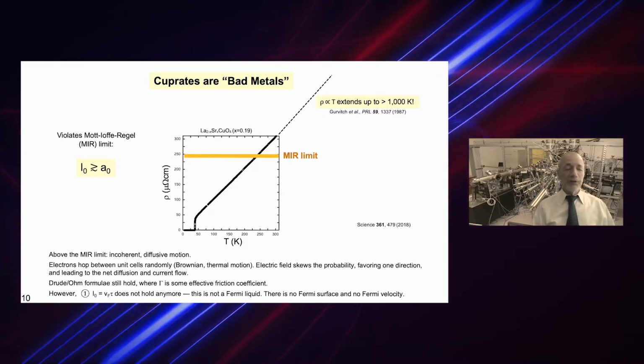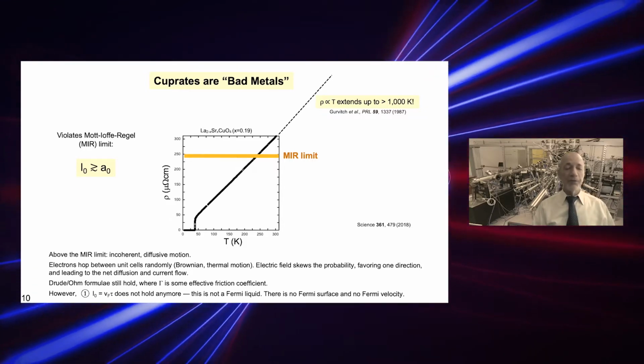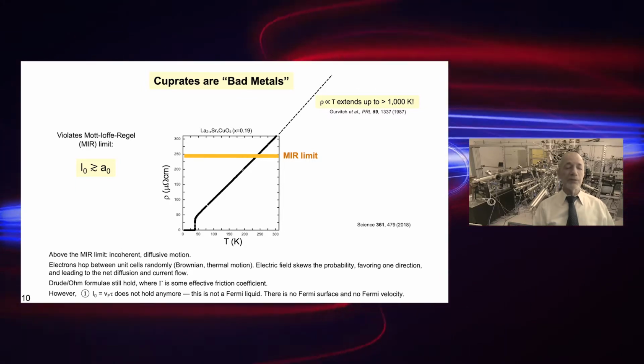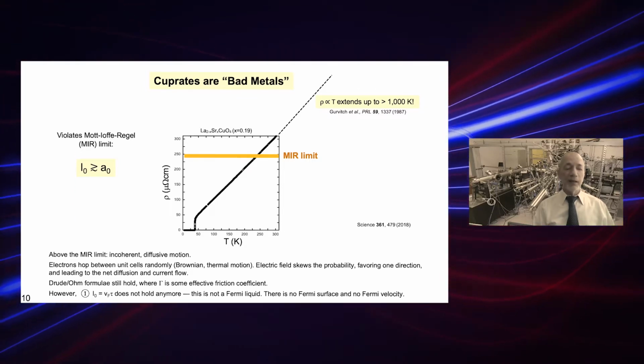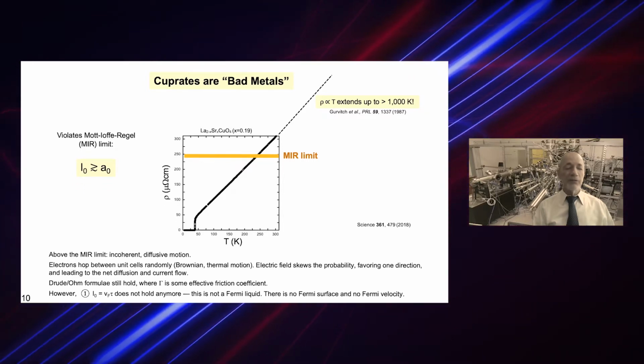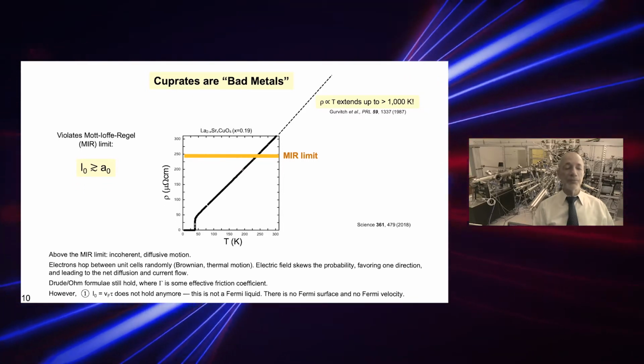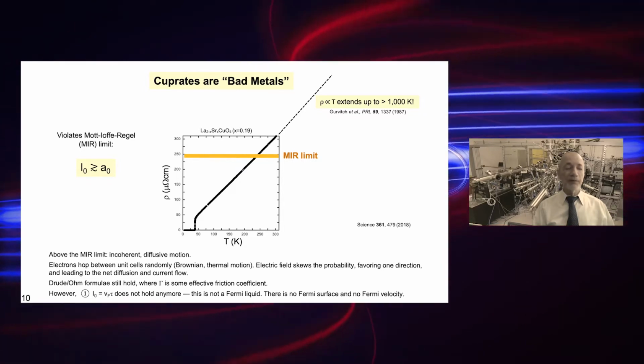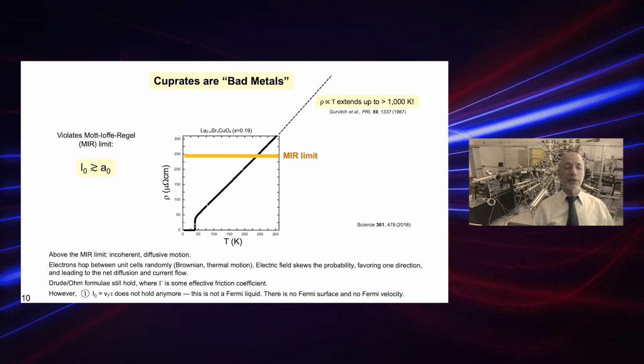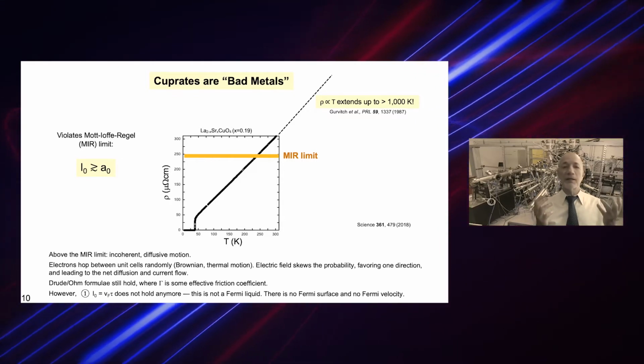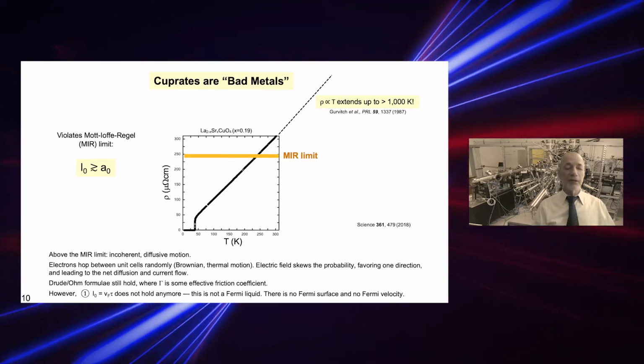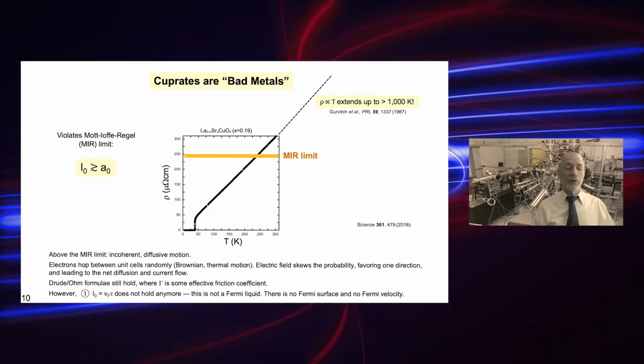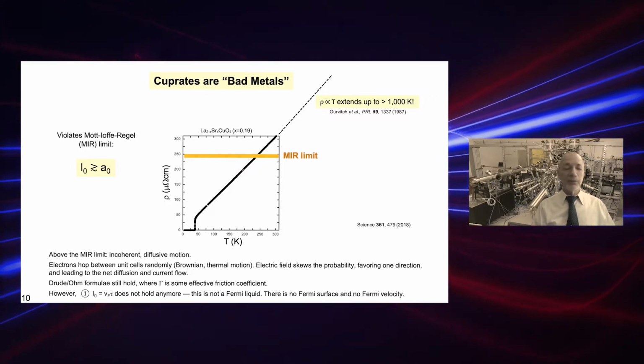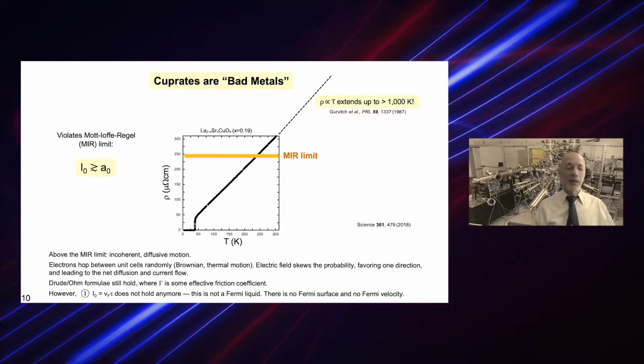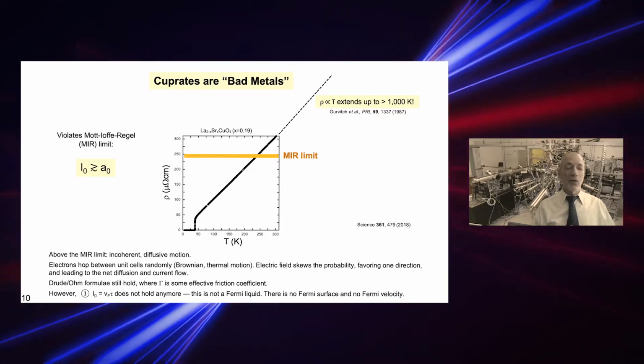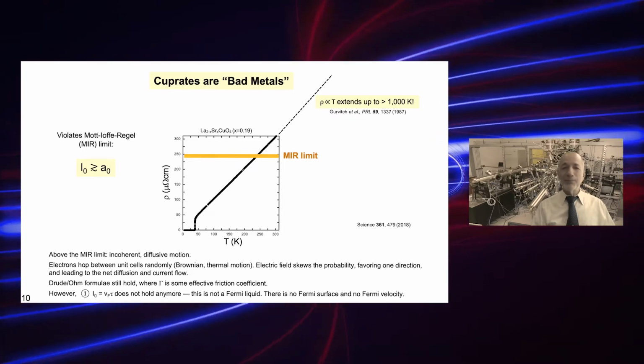Apart from the T-linear dependence itself, there are two other major discrepancies. The first one is that, unlike in standard metals, the resistivity does not saturate at high temperature. And it should, since the mean free path cannot be smaller than the distance between the atoms. There is nothing to scatter electrons on. This is known as the Ioffe-Regel limit or Mott-Ioffe-Regel limit. And this limit is grossly violated in cuprates. This is colloquially known as the bad metal behavior.